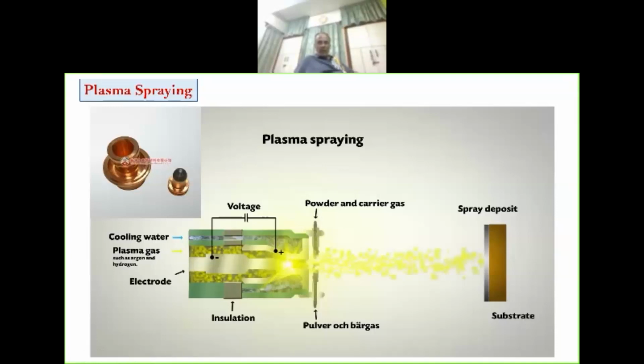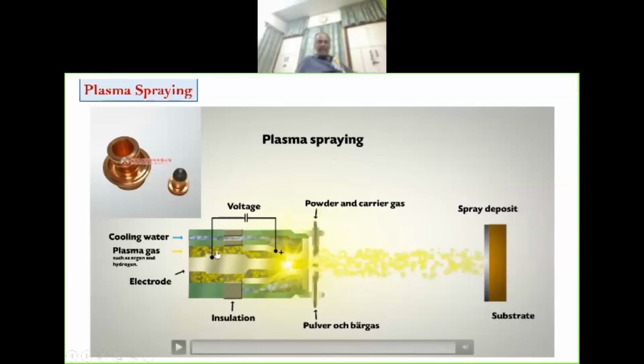Okay. What do we do? We start an arc. Gas in contact with the arc will ionize. When it is ionized, it conducts more electricity, so current increases. More ions and electrons, more current, more heat, more gas, more current, more heat. In a small volume of gas, I keep on injecting a large amount of energy. Commercially available plasma is at 50 to 100 kilowatts. It can be more. One constraint is heating. If the temperature is too high, the entire encasement, electrode and nozzle will melt away. So the procedure is good for making a sun if you can contain it.